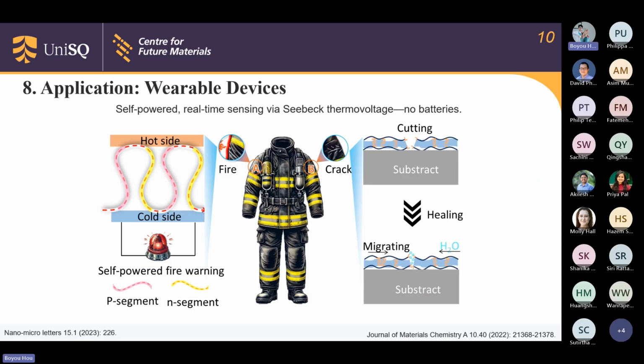With the mechanisms in place, let's see them in practice. This slide summarizes self-powered warning and self-healing coatings reported in some literature. Researchers print thin P and N-type thermoelectric strips on fabric. When the outside of the suit is hotter than the inside, the straps generate a thermal voltage, so no battery is needed. A tiny circuit reads that voltage and gives a vibration or beep. Placing the straps near hot spot areas such as shoulders, sleeves, and chest gives the earliest cue for firefighters and first responders.